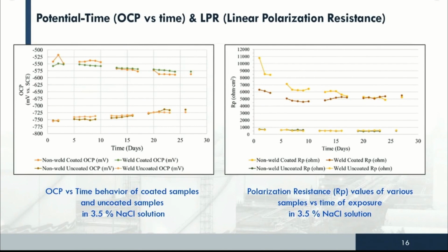The top lines show the welded and coated and unwelded and coated, and the bottom ones show the bare steel metal. As you can see, the decrease of potential of the active metal indicates that the top ones have a passive layer, or something protecting them. We also observed here that the open circuit potential did not really differ between welded and non-welded.